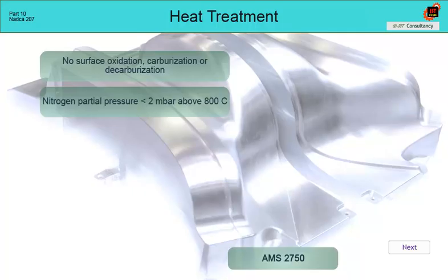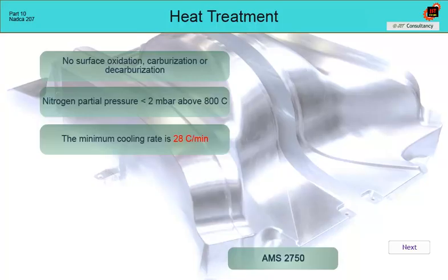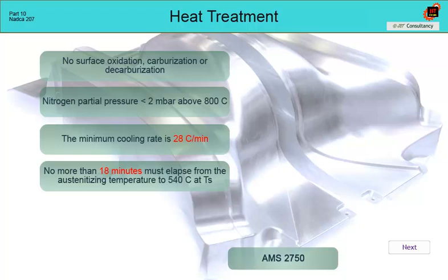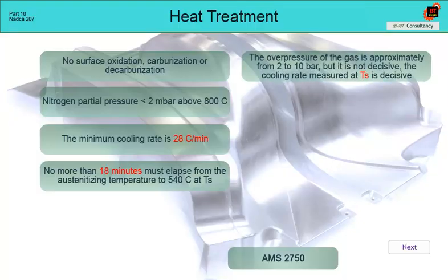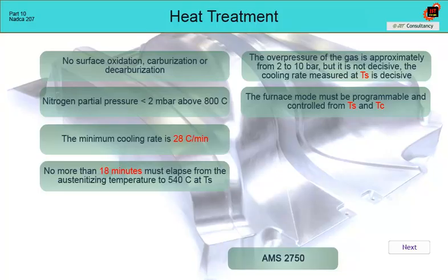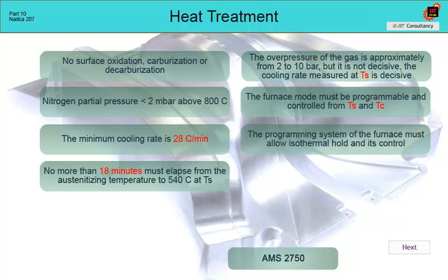To avoid slow cooling problems, NADCA 207 specifies a minimum cooling rate of 28 Celsius per minute, measured from the surface thermocouple Ts, and this rate needs to be maintained in the range from the austenitizing temperature to 540 degrees Celsius. The minimum nitrogen gas overpressure is not defined, but it is expected that it will be from 2 to 10 bar absolute. The vacuum furnace for NADCA 207 must be programmable and capable of working with a minimum of 2 batch thermocouples, one designated as Ts on the surface of the part, the other as Tc in the center of the part. The furnace programming system must be able to control the isothermal hold and automatically adapt it according to the actual temperatures Ts and Tc.